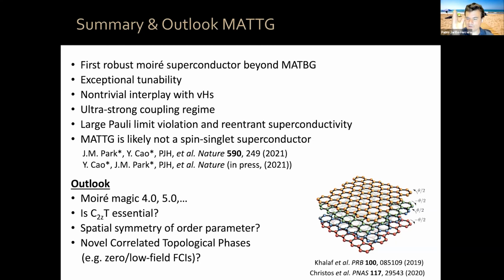Superconductivity mostly occurs between filling factors 2 and 3 and -2 and -3, etc. Okay, it's also strong coupling superconductivity in both cases. The superconductivity Tc is maximum when the density of states is minimum, so it's very unconventional. And here in this slide, precisely in this paper and in a subsequent paper, the Vishwanath group suggested that this alternating twist angle geometry, so this picture is for 4 layers, you can also have 5, 6 layers of alternating twist, respects C2T symmetry, and they claim that the C2T symmetry is a key ingredient to realize this robust superconductivity, okay?